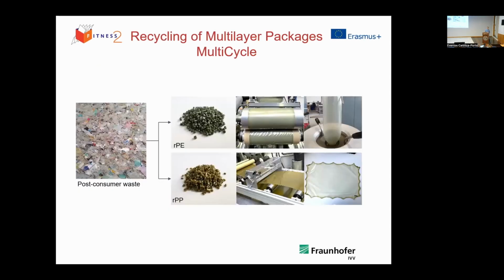And how did that work? For example, here we see a post-consumer waste, and we first extracted selectively the polyethylene, and we were able to process the polyethylene with, for example, cast film extrusion, but also blow film extrusion. And this was completely feasible within usual processing parameters, which were also applied for virgin PE. And after we've extracted the PE, we took the residue, and then we extracted selectively the PP. And this was also feasible. And the PP was also processable and even stretchable. So in the picture on the very right, you can see a stretched PP film, and you can't see any holes or something like that. So the mechanical properties were very, very good.